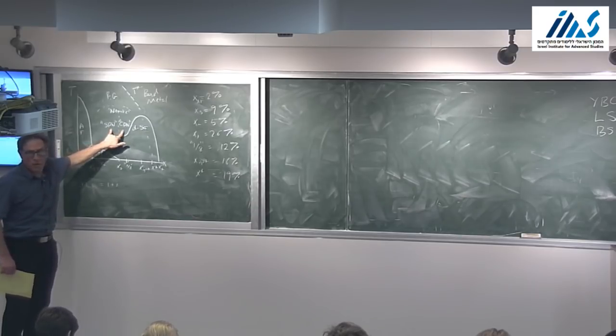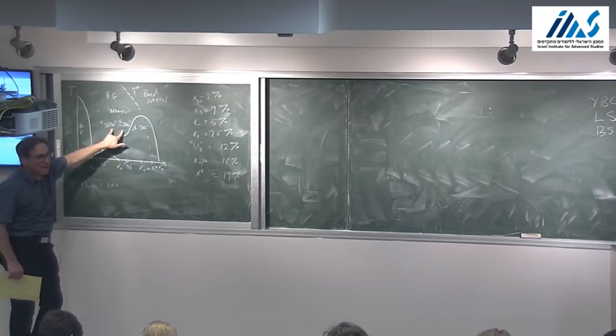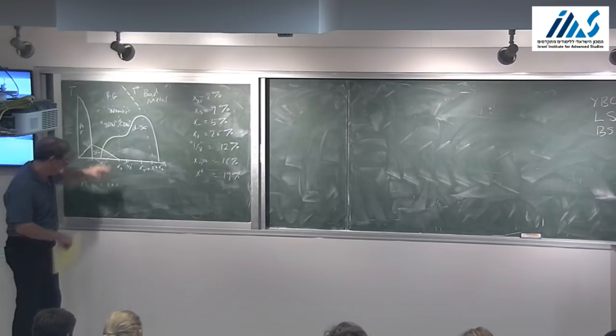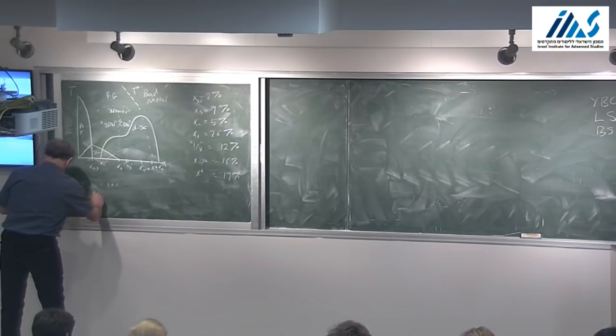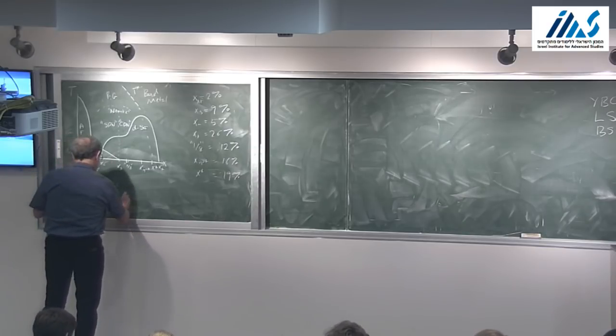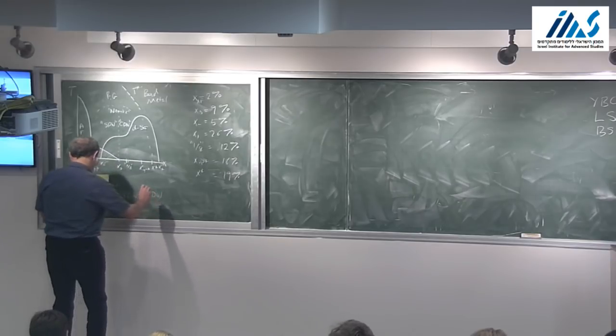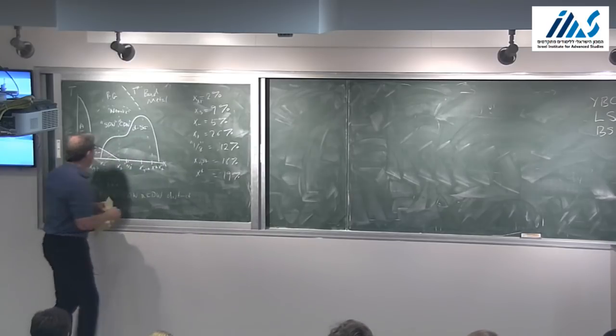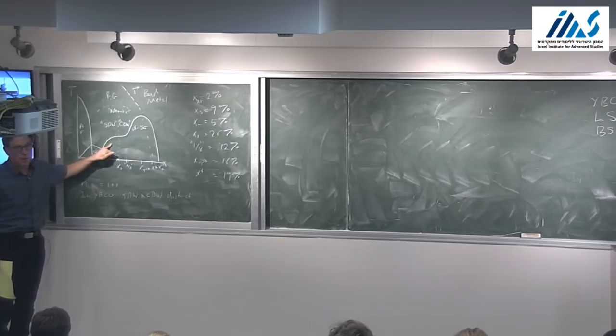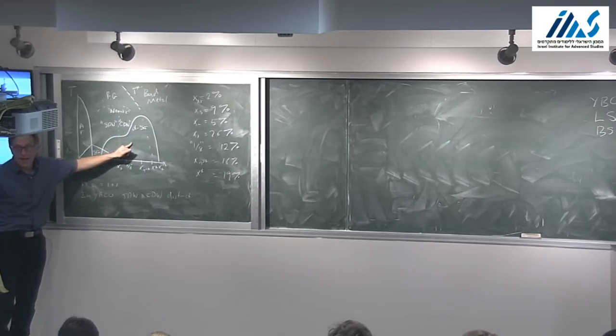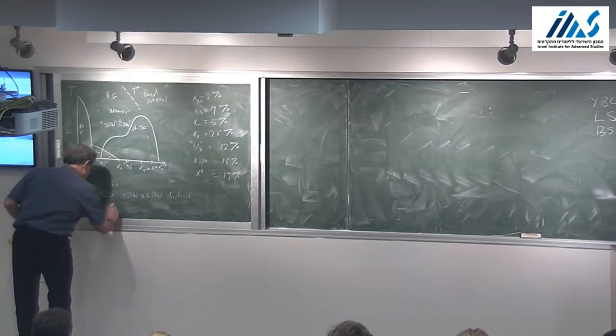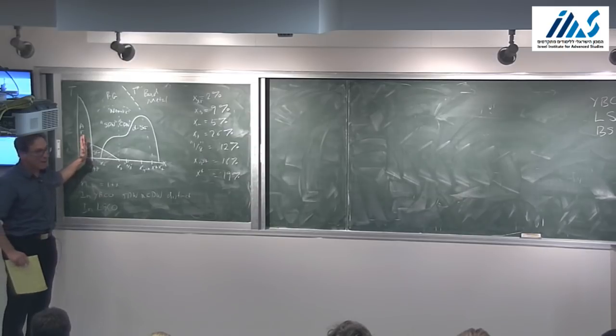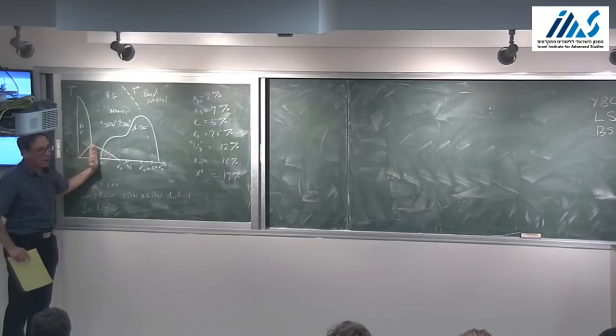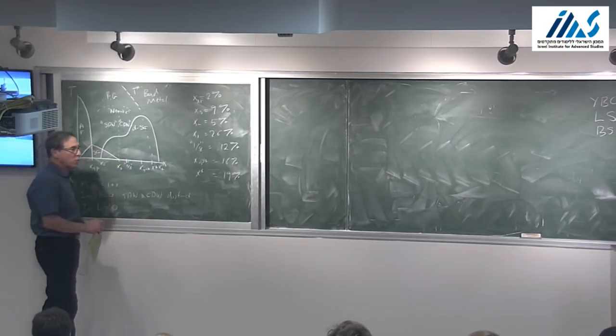And also here I've drawn the one thing that's different between two families, YBCO and LSCO, is this interplay between charge density wave and spin density wave. So maybe I'll put that here as a note. In YBCO, as I've shown here, the SDW and CDW are distinct. That is to say, first of all, the ordering vectors are mutually incommensurate with each other. And it seems that if you have one, you don't have the other. They seem to fight. In LSCO, both short-range SDW and short-range CDW order exist over this whole range of doping. They occur together, and they're mutually commensurate with each other.